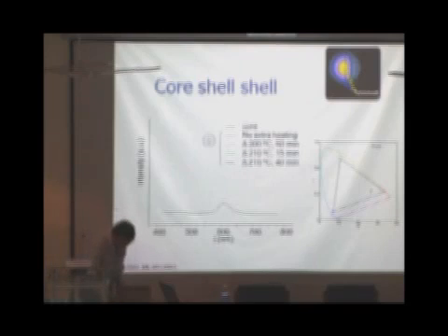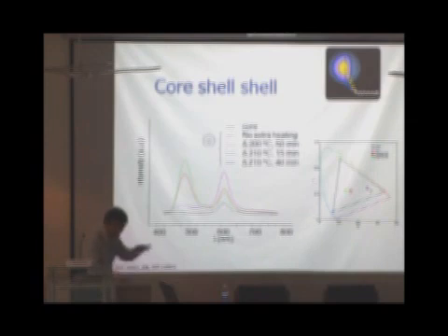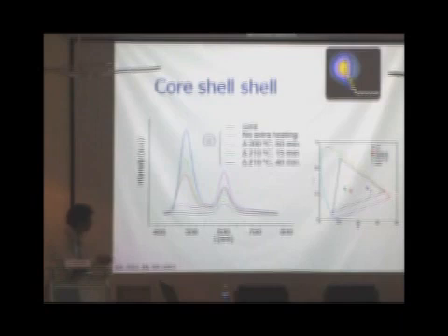So that's interesting. I keep on making a shell around it, and I start getting some emission from the shell, and I do some tricks over there, which are basically heating and beating of these nanoparticles, nothing more. And you can actually play around with the intensities. And over there, what you saw is a traverse through the CIE coordinates, touching the exact center of the white point, which is 0.33, 0.33. But actually white is more well defined as a region rather than a single point.